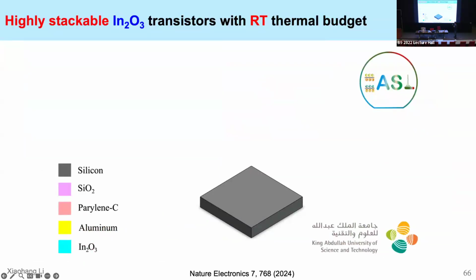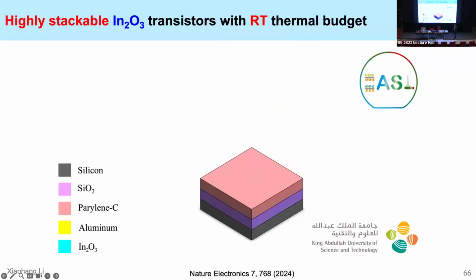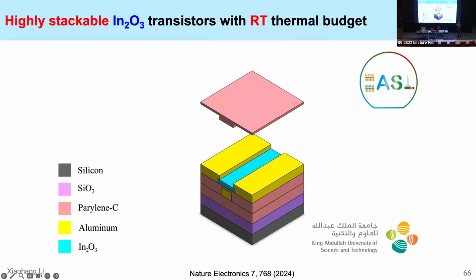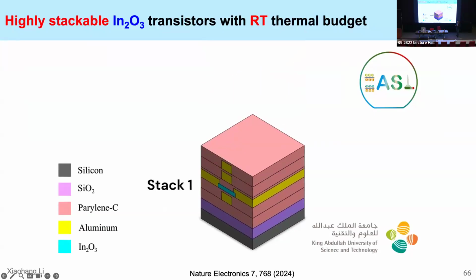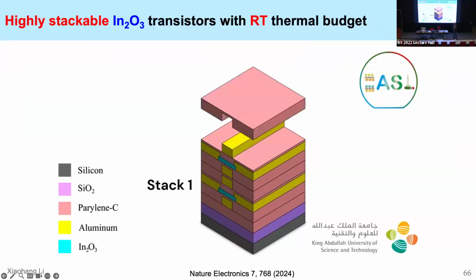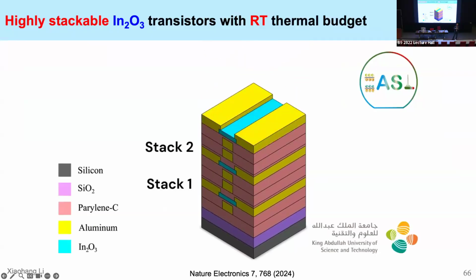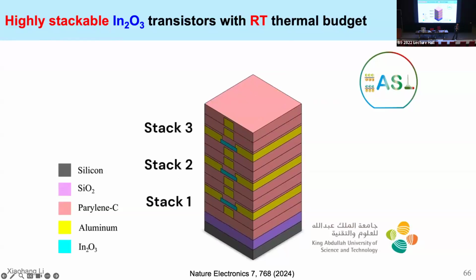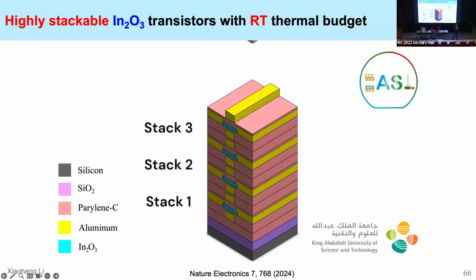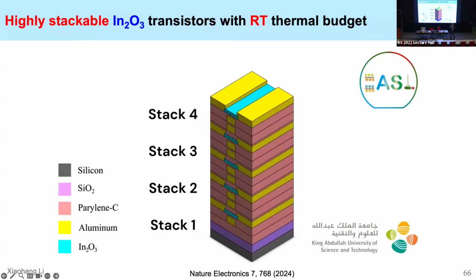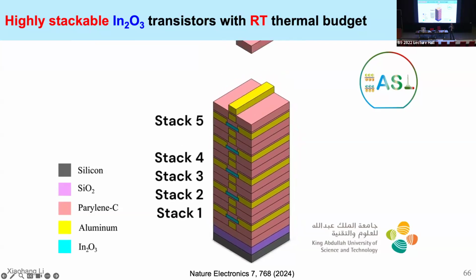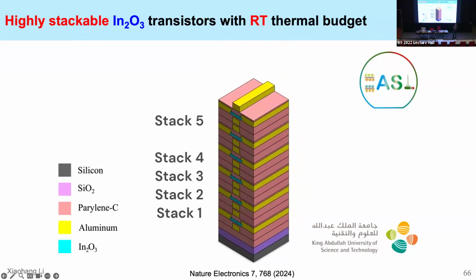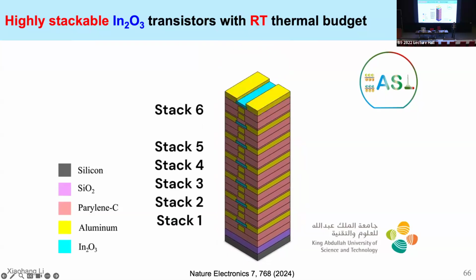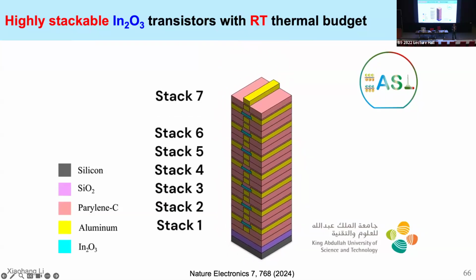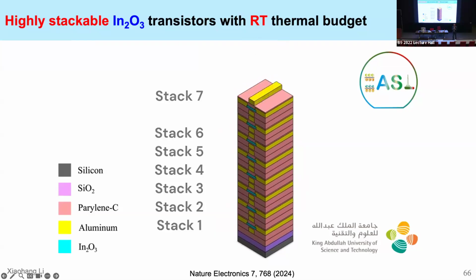So this is the process flow. Again, it's a short clip. We started from a silicon substrate, okay, and then we have to refine and optimize the process where we have to deposit tens of layers of different semiconductor active and passive layers on top of each other. That includes the insulation layer, buffer, and the active layer, which is a 5 nanometer thick indium oxide channel transistor, and also metal for the source, drain, and gate. On top of that, we have to use the dielectric as well.